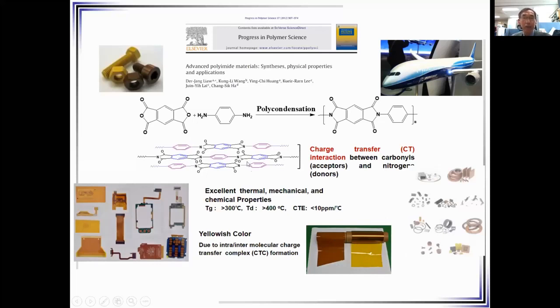Why? As you know, with the chemical structure like this, polyimide can be synthesized by mixing dianhydride and diamine, and you make the polyimide by kicking out the water. If you see the chemical structure, this is all aromatic rings, so this is really highly thermally and mechanically stable. But because they have lots of electron acceptors and donors, they inherently form charge transfer complexes. Because of the charge transfer complex formation, they always have this yellowish and brown color. But if you use this as the matrix for airplane or engineering parts or display, at that time it doesn't matter.